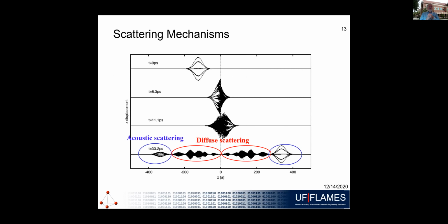Finally, the scattering mechanisms. This is actually a very old image from work I did a long time ago. And this is showing a scattering event of sending a phonon package on the top line into scattering into some sort of boundary. And what we're seeing here is the parts which are reflecting and the parts which are transmitting. So this first part is basically acoustic model type scattering. This is diffuse type model scattering. And this is a direct indication that these classic approaches are both useful, but are both limited also in that they don't describe this interaction.